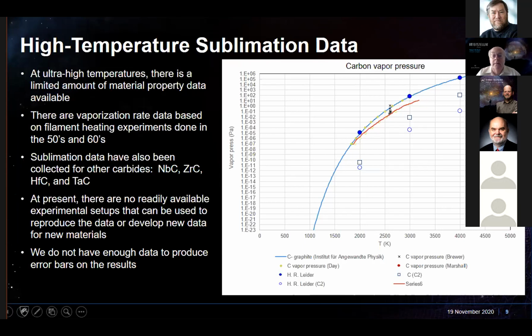A lot of this testing was done in the early 50s and 60s, and there are not a lot of testing facilities out there, right? If you say I have this piece of material and I want to measure its vaporization up into the 4000 C, 4000 K range, that's not a trivial test to do. There's not a facility set up where you just give them the material and they give you results. So there's time and energy put into just figuring out how to do the testing, what testing you have to do, and how you verify those tests.